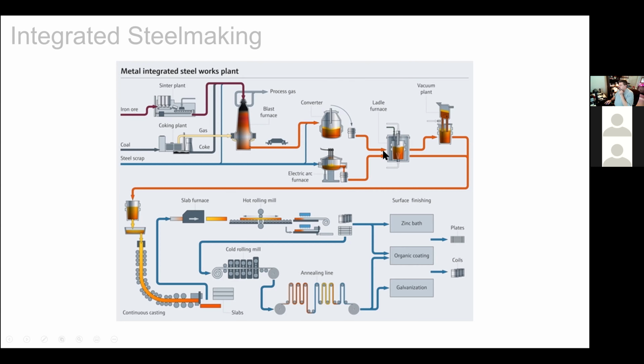And the whole idea here in the ladle furnace is to carry out reactions that are reducing. So in the EAF, we carry out a lot of oxidation reactions. And then in the ladle furnace, we do things like try to remove sulfur, which is a reducing reaction. It requires that you reduce the oxygen content in the steel, the oxygen content in the slag. And we adjust the temperature. And this unit essentially paces what's happening in the steel shop and then coordinates with, you may go through some vacuum treatment, but in a lot of cases, you go from the ladle furnace to the caster.